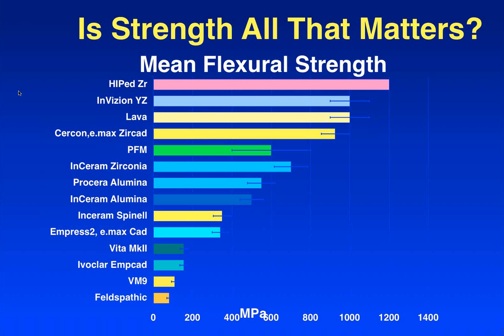When we do strength testing for our materials now, we make sure that the finish is the same as it's going to be in the mouth, because it doesn't make sense to make these highly polished mirror finish samples, because that's not what's going to happen in the mouth. So here's a chart with pretty much all the ceramic materials that we can have and that we're using. The zirconia is up at the top end, very high strength materials, all the way down to veneering porcelains that go on top of ceramics or on top of metals.